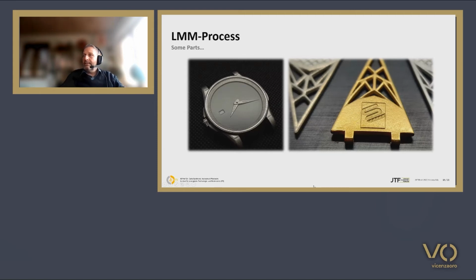So here are some parts. What you see on the left side is the watch case. And this watch case is as printed. So you see here the printing lines on the surface, but this designer said he wants to have this special appearance just to feature the printing process. On the right side, you see a flat part. This has a golden appearance, and that's because it's electroplated. So that's a stainless steel part. So we cheated here a bit.